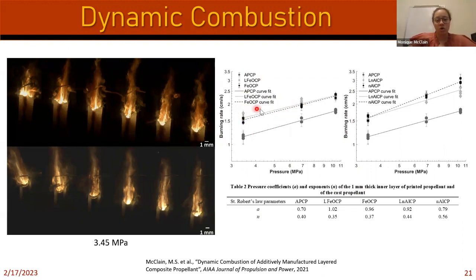And if it's no L, essentially that means we're comparing the linear burning rate of just normal iron oxide propellant. And then we have APCP, which is just the linear burning rate of normal ammonium perchlorate propellant, right? The slower burning one. And on this plot, it's labeled similarly, but the additive is nano aluminum instead. So in general, we were comparing these. This curve here is just the normal slow burning propellant.